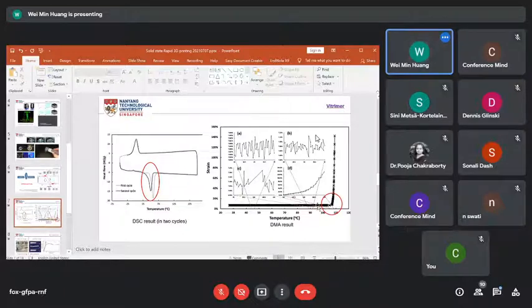And then, if we heat up to over here, about 100 degrees, you can see the material is still elastic, although its elasticity is not as good as shown over here and here. Which means that at 100 degrees, somewhere here, the material is still able to maintain the shape. Only when we heat up to over here, close to 110 degrees, the material starts to gradually deform. That is because the material is able to flow. So until we heat up over here, the material is able to flow.